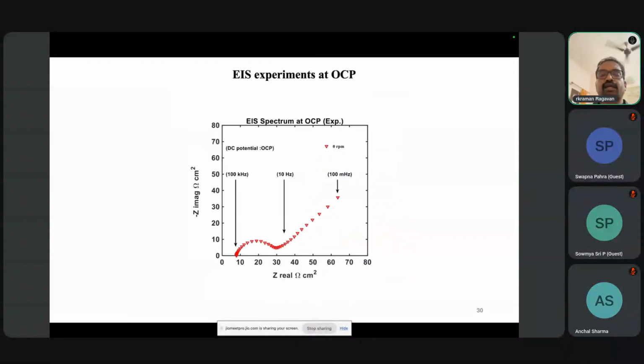Let's do that. First I am doing it at open circuit condition. When I do it at open circuit condition, I have certain impedance data. You can see there is one value here. This is due to solution resistance, and I have a semicircle here. The semicircle is due to the charge transfer resistance of the ferro-ferri species. After that, I see a 45-degree angle. I see a line, right? At 0 RPM, I see a line at a 45-degree angle.